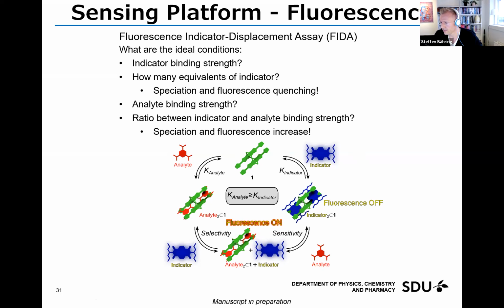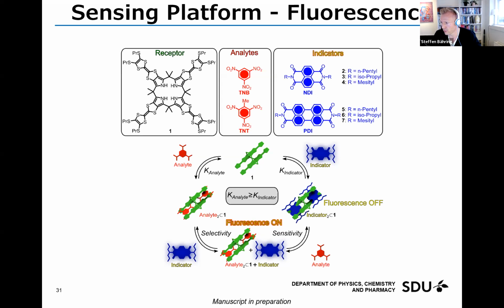Because as you can see from the TNB and the TNT, they fit very nicely inside the cavity of the TTF Calixpyrrole. They have both CT interactions and dual hydrogen bonding interactions. But these fluorophores, based on the NDIs or PDIs, are mostly centered around CT interactions because the distance between the two carbonyl moieties is too great for them to effectively hydrogen bond inside the cavity. And I'll show you shortly.